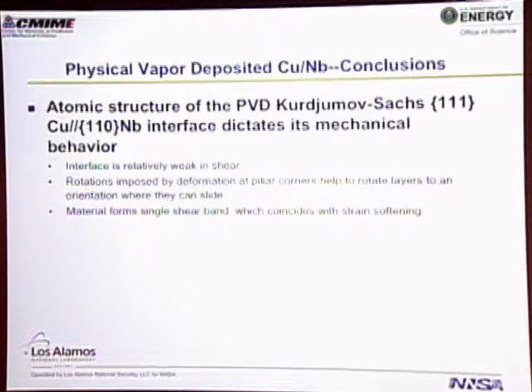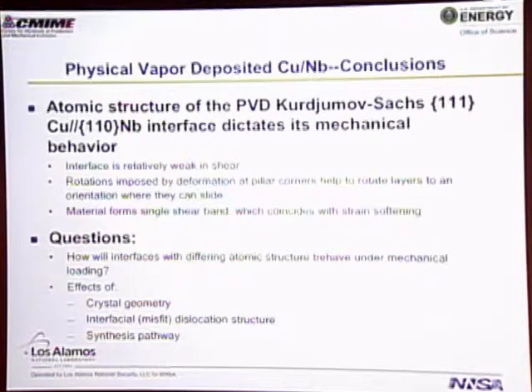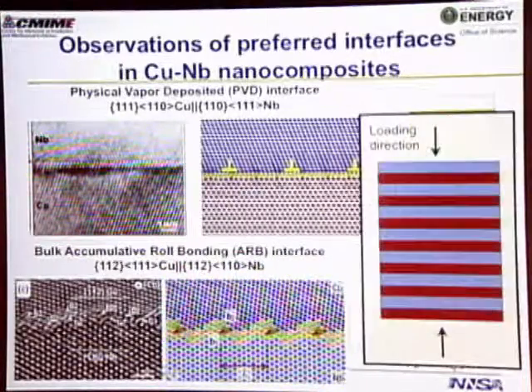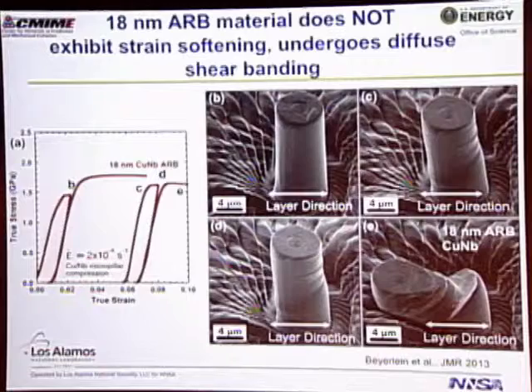If we imagine crushing this pillar, we rotate our layers a little bit on the corners, just as it's just the way that the stress state of the pillar compression test works. And then we form this single shear band, and that coincides with this kind of softening event that we see. So the question is, what happens if we change the interface? So we'll move to this roll bonded interface and crush it in the same way.